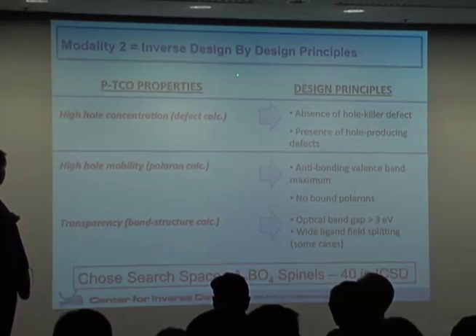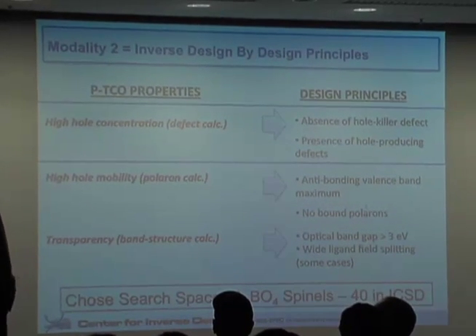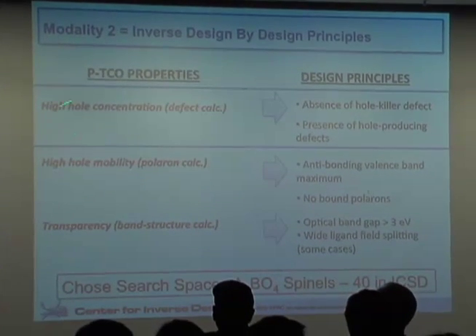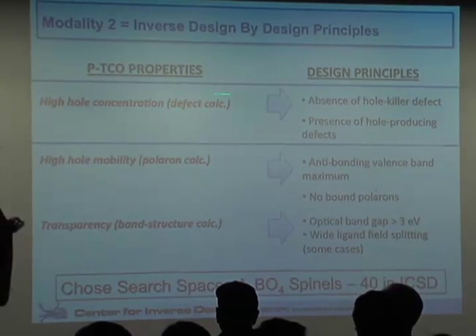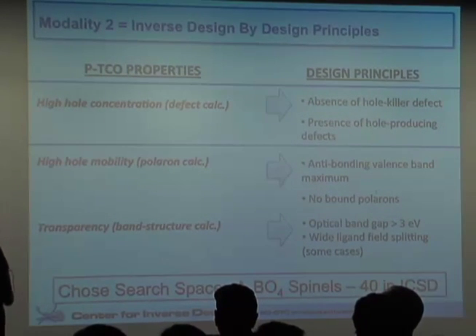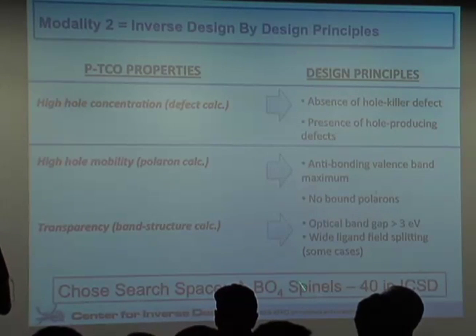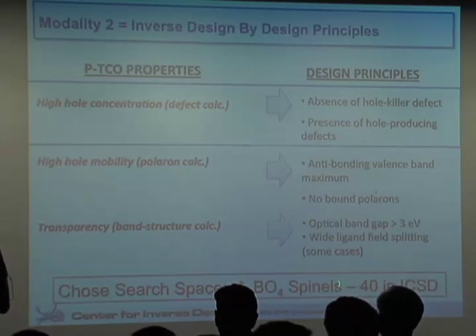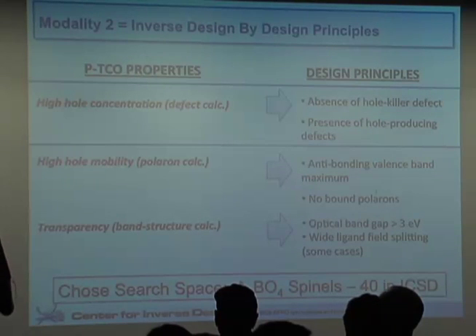And so if we think about making a p-type transparent conducting oxide, we need to have high hole concentrations, so we need to do a lot of work on defect calculations, and that's been our starting point. And eventually we need to think about hole mobility and transparency. And so with respect to thinking about high hole concentrations, we've taken a look at these spinel systems. We've looked at about 40 of them in the ICSD database. I'll talk about those in a moment.